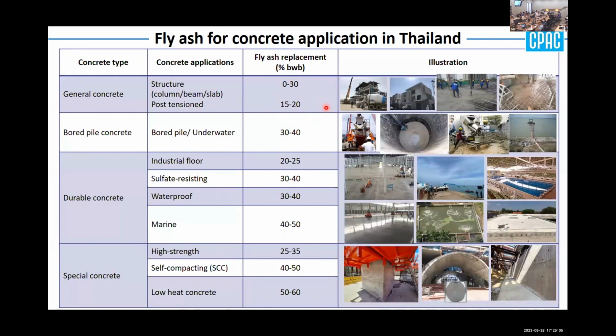For post tension, as I mentioned, in Thailand we use it for high-rise buildings, so we need some fly ash to give better pumpability of the concrete. For bored piles, we replace fly ash around 30 to 40%, even in underwater concrete work. And if we talk about durable concrete, as I mentioned, industrial floor, we use around 20 to 25%. For sulfate resistance, we use around 30 to 40%. For waterproof concrete as well, and marine concrete, we use around 40 to 50%.